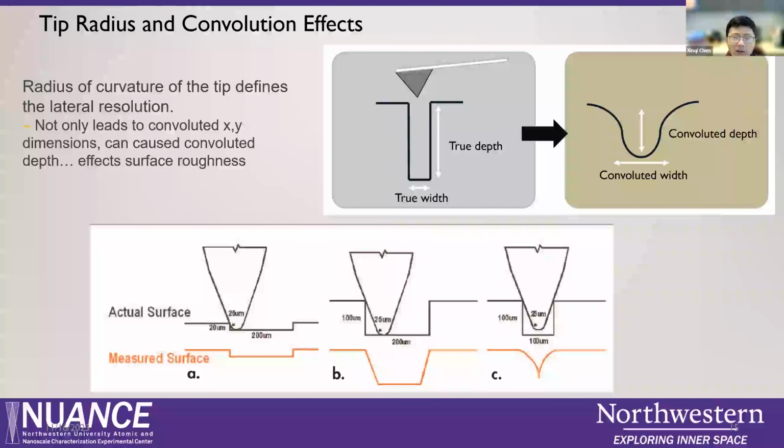It's 100 micron. So this tip cannot reach the bottom. They give you an artifact like this shape. So that is a different feature. And when you measure the features of your surface, you have to consider the shape of the radius. Okay. Next